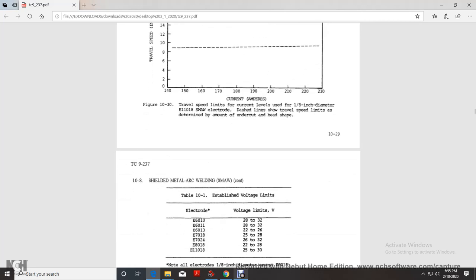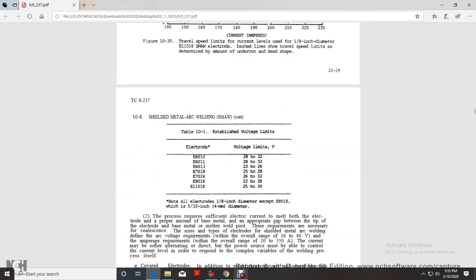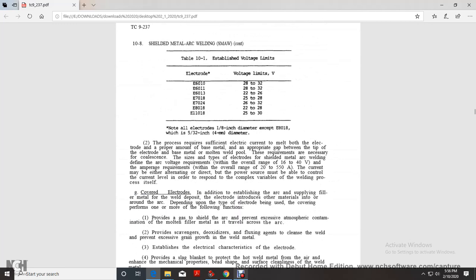Table 10.1 shows the established voltage limits, and the process requires sufficient electrical current to melt the electrode and the proper amount of base metal, with the appropriate gap between the tip of the electrode and the base metal with the molten weld pool, to define the arc voltage requirement with an overall range of 16 to 40 volts. Amperage required has an overall range of 20 to 550 amps.